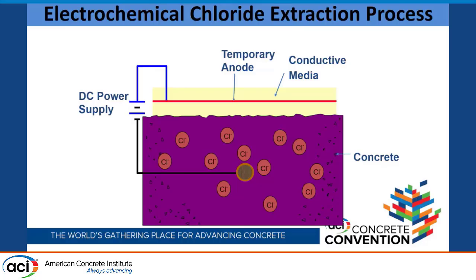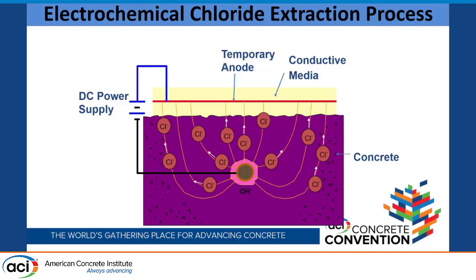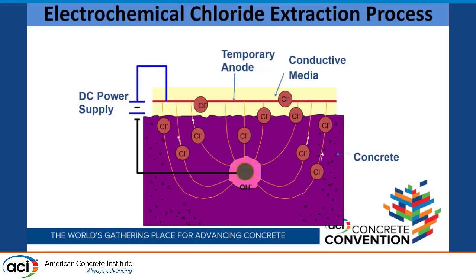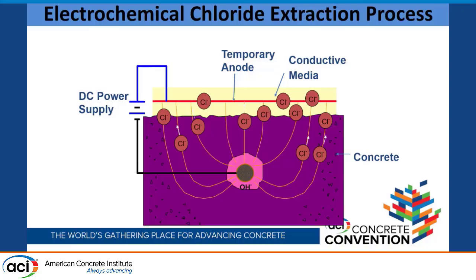And in graphical form, it happens like this. The system is applied on the surface, but exterior to the concrete. It's connected to a DC power supply. When you turn it on, you charge the rebar negatively. You charge the system on the surface positively. You keep everything wet so that the chlorides can go into solution within the pores of the concrete. And then they tend to move in the direction of the current flow lines, and they progressively move away from the rebar and towards the surface.